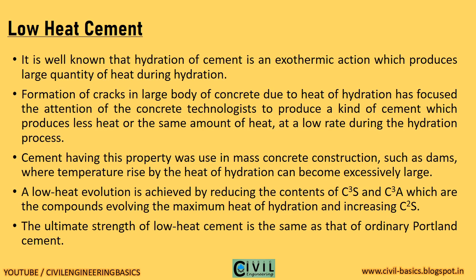Low Heat Cement: Hydration of cement is an exothermic action which produces a large quantity of heat. Formation of cracks in large bodies of concrete due to heat of hydration led concrete technologists to produce a cement which produces less heat or the same amount of heat at a lower rate during hydration. Cement having this property is used in mass concrete construction such as dams, where temperature rise by the heat of hydration can become excessively large. A low heat evolution is achieved by reducing the contents of C3S and C3A — the compounds evolving maximum heat of hydration — and increasing C2S. The ultimate strength of low heat cement is the same as that of ordinary Portland cement.